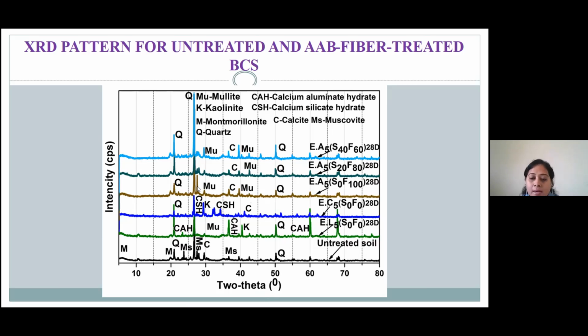The dominant clay mineral present in the untreated soil is montmorillonite, and the addition of fly ash or slag helps alter the diffraction pattern. The flatter surfaces of the diffractogram indicate the amorphous phases in the fiber AAB matrix.